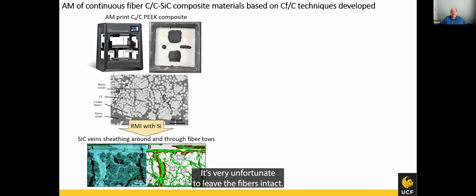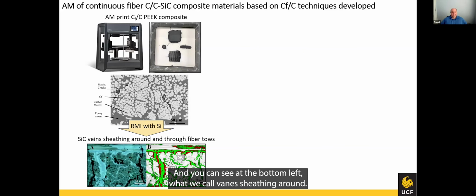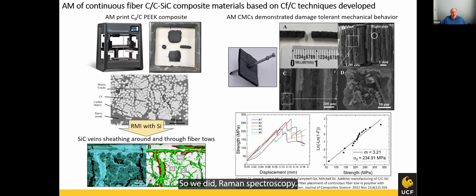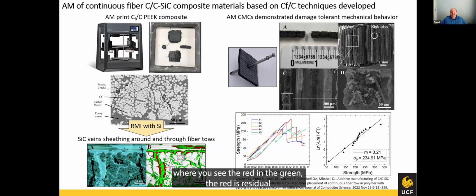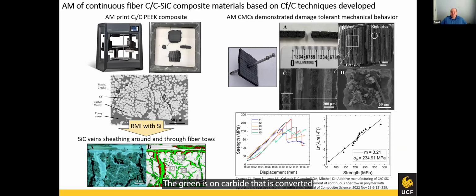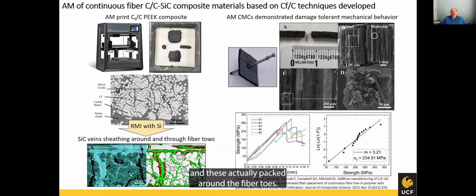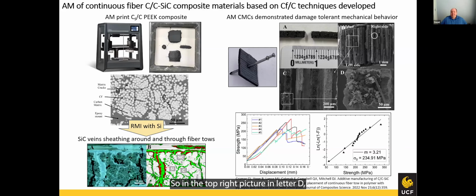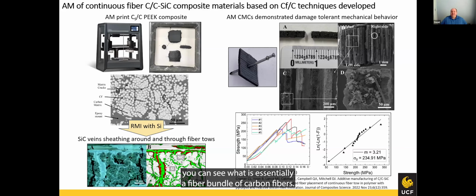It's very fortunate to leave the fibers intact, and you can see at the bottom left what we call veins sheathing around. So we did Raman spectroscopy, and you can see in the lighter areas and on the right hand side where you see the red and the green, the red is residual silicon that is always left when you melt infiltrate. The green is silicon carbide that is converted, and these actually packed around the fiber tows. So in the top right picture in letter D, you can see what is essentially a fiber bundle of carbon fibers, and that monolithic material that's around it is silicon carbide and silicon.